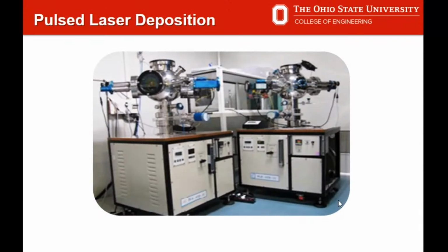This is another technique that I also used during my PhD. This is pulsed laser deposition. As I mentioned, in RF sputtering you are using some kind of plasma, which is injected by argon ions. But in the case of pulsed laser deposition, you are using a laser to ablate the target so that it can be deposited on top of the substrate. So the basic difference you can see is that one is using plasma, and the other is using a laser.